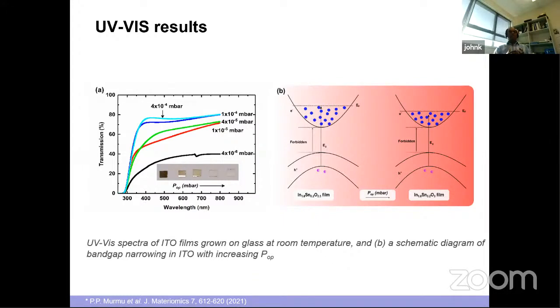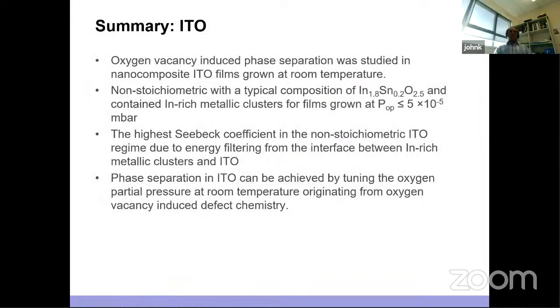But here the context is more on transparent thermoelectrics, because it is a transparent material and it is reasonably cost effective as well. There are many methods you can use to make indium tin oxide thin films, and a lot of low cost methods as well. The key factor here is tuning the conductivity and Seebeck coefficient. Oxygen vacancy induced phase separation is the factor by which we have nanocomposite ITO films.